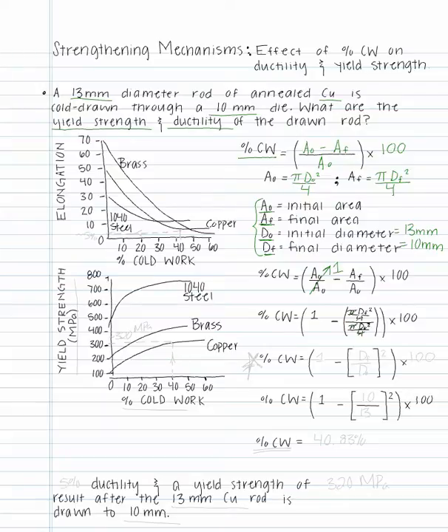we can see that percent cold work equals (1 minus (D_f / D₀)²) multiplied by 100. And this is the final equation that we will be using to find the percent cold work in this problem.